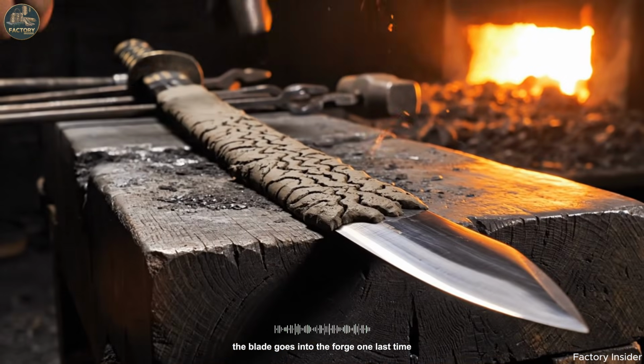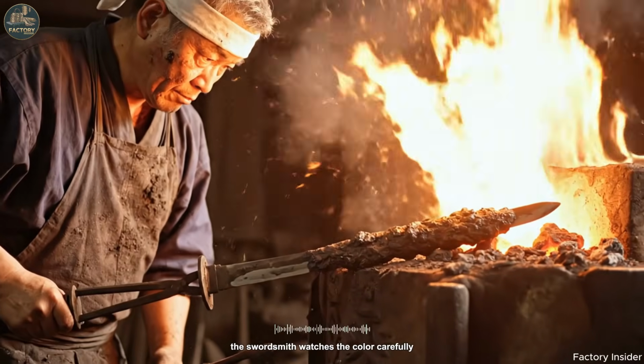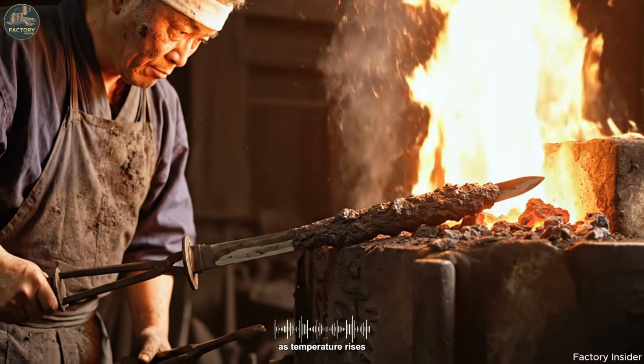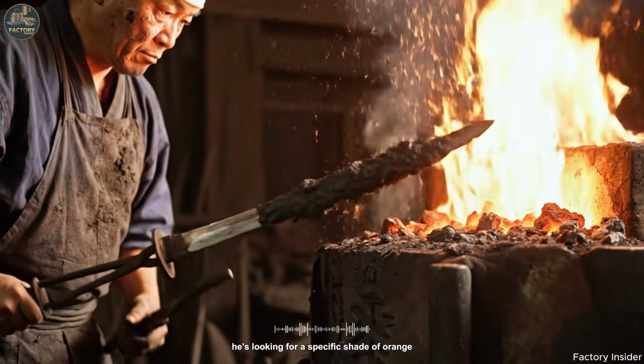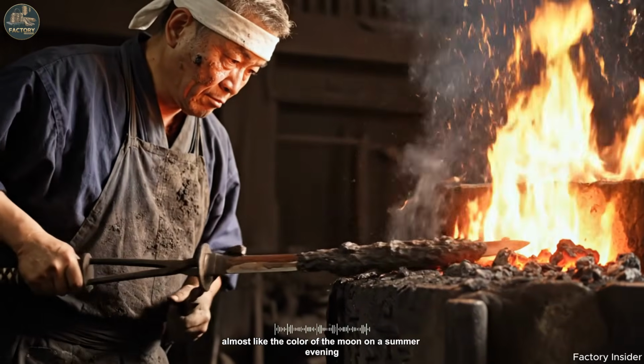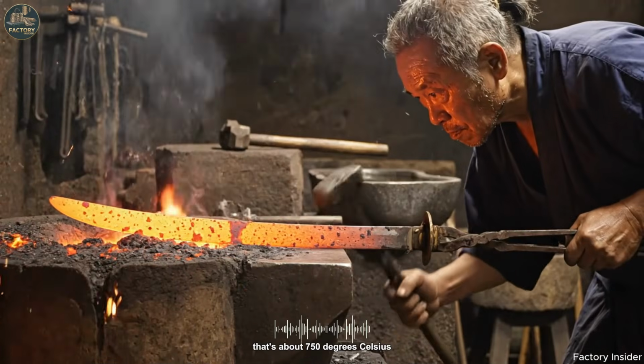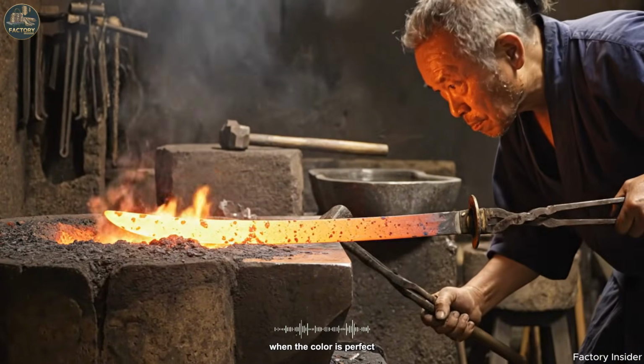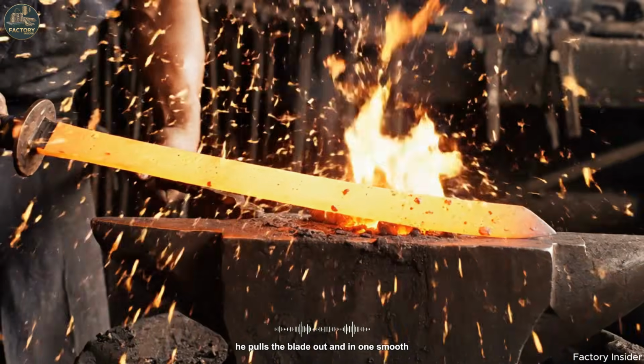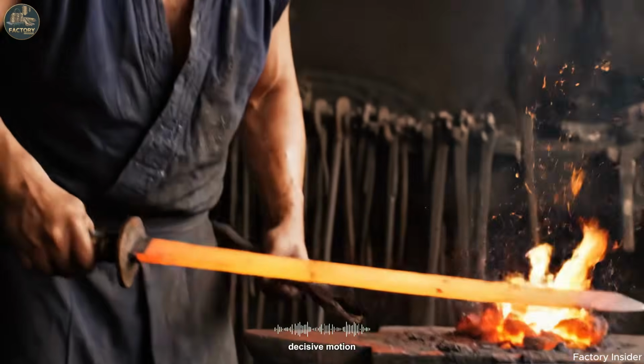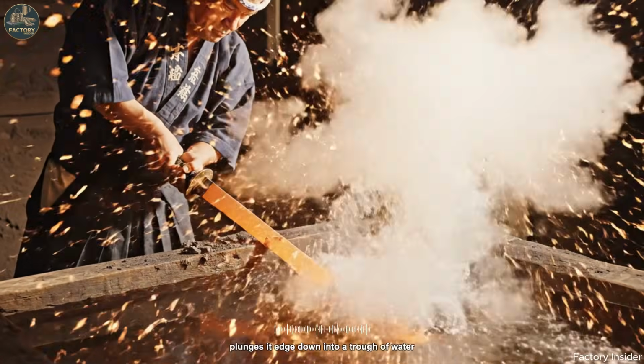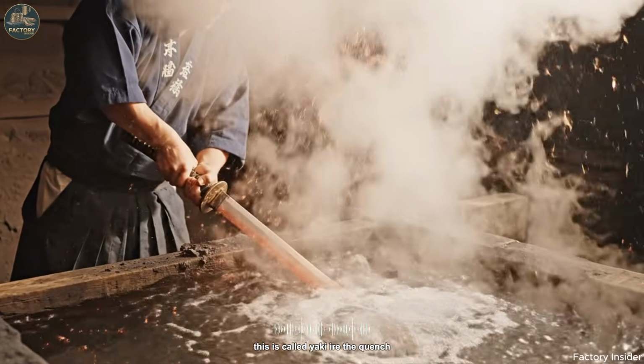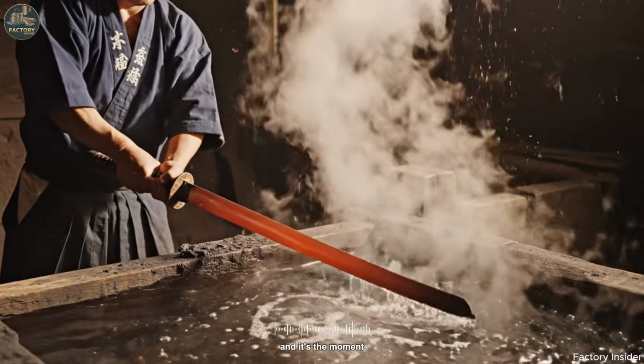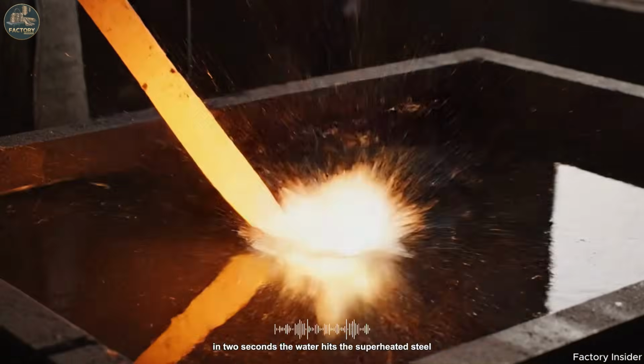The blade goes into the forge one last time. The swordsmith watches the color carefully as temperature rises. He's looking for a specific shade of orange, almost like the color of the moon on a summer evening. That's about 750 degrees Celsius. When the color is perfect, he pulls the blade out and in one smooth, decisive motion, plunges it edge down into a trough of water. This is called yaki-ire, the quench, and it's the moment where years of work can be destroyed in 2 seconds.